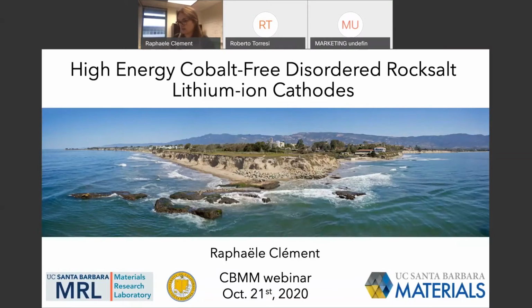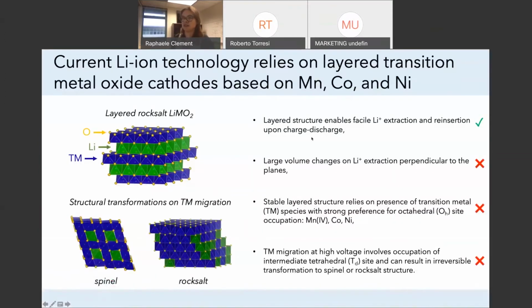So to start my talk, I'd like to first discuss layered compounds that you're all familiar with. So these are the NMC type cathodes that you are familiar with. And so these types of materials are popular because the layered structure enables facile lithium extraction and reinsertion during charge and discharge from the lithium layers in these materials. However, there are certain shortcomings of these compounds. And one of the major shortcomings is this large volume change as you extract lithium from the lithium layers. And so you get an expansion of the structure along the C-axis, which is perpendicular to these layers here.